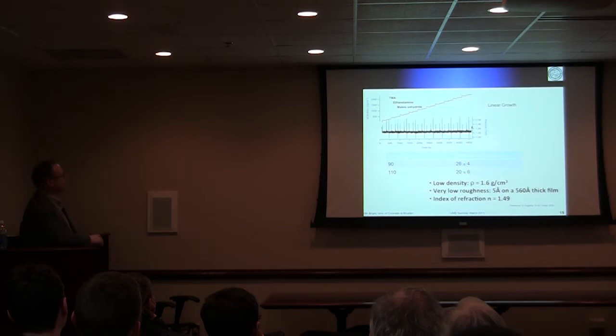Just as earlier examples of MLD coatings that we've been working on, there is the coating called alucone, or metalcone in general. You can use different metals other than aluminum. This is an organic molecule in what's called an ABC reaction rather than just an A and B reaction, based on ethanolamine. This ABC system is also quite controllable. If you look at the measurement, it's linear growth with time. The nice thing about it is, again, a very low temperature deposition process.